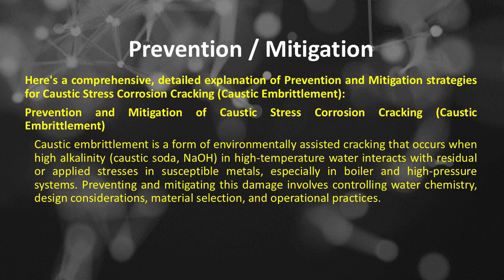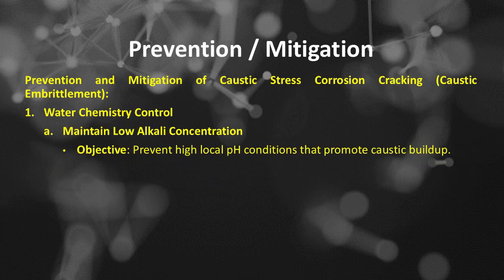Preventing and mitigating this damage involves controlling water chemistry, design considerations, material selection, and operational practices. Here is a comprehensive, detailed explanation of prevention and mitigation of caustic stress corrosion cracking or caustic embrittlement. Includes, number 1, water chemistry control. Number A, maintain low alkali concentration. Prevent high local pH conditions that promote caustic buildup.